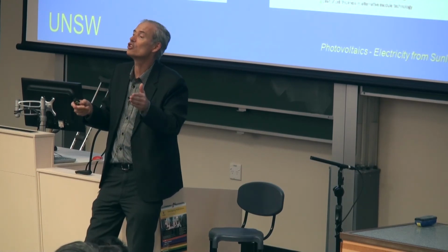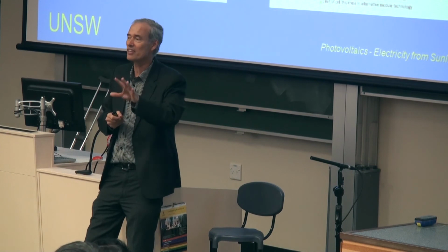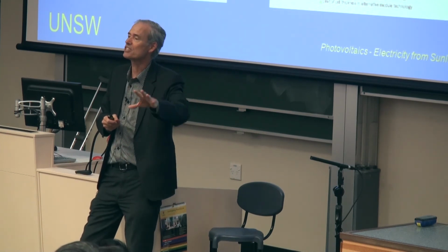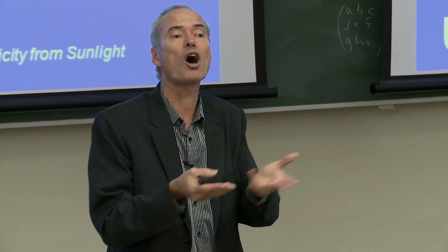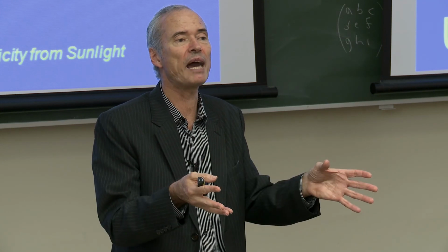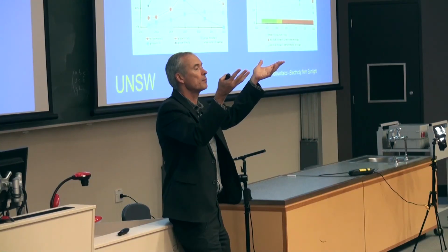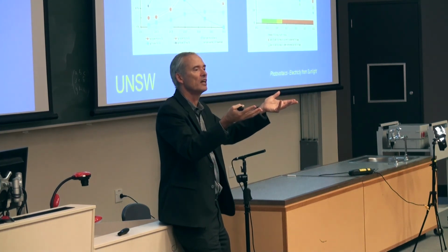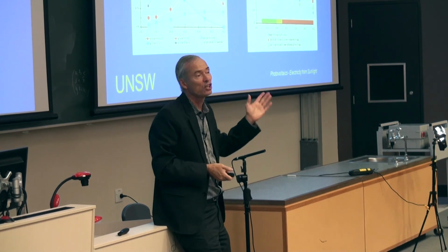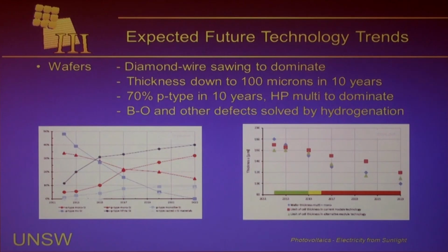And so what they're doing is they're actually using a higher purity of silicon. Now I know that sounds like we're going in the wrong direction, but the cell manufacturers are looking at how the price of the high purity silicon is dropping and how cheap it's become, and they're saying it's not a problem anymore to use that silicon and therefore produce the high performance multi. Smaller grains, lots of grain boundaries, but ones which don't get the contaminants because we're using high purity silicon. Therefore, we make wafers that are the same quality throughout the entire ingot, no more non-uniformity like we used to get, and we've got a material that's not just uniform, but it's good in quality and able to make highly efficient solar cells.